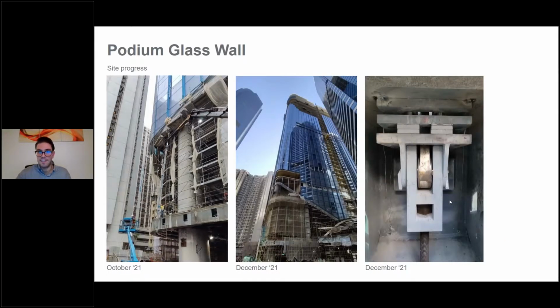And luckily, actually today we had some other pictures coming from Yanchi, because the pre-tensioning of the rod has started. So at the moment it is one of the first sequences of pre-stressing. They will pre-stress all the rods up to 50%, then they will move up to 80%, and then 105%. And you can see here the zoom in of the detail at the bottom, where we have the pin. This is the temporary threaded bar for pre-stressing.